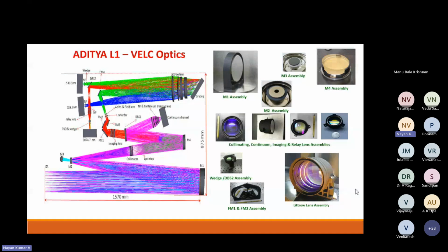And then we also had a silicon carbide mirror just to throw out that central disk, because this is an internally occulted system where the solar disk has to be thrown out, and we use only the corona for subsequent studies. So we made a silicon carbide mirror also with the help of ARCI. We got CVD coating done on that sintered silicon carbide, and then developed a polishing recipe to get this mirror to very low roughness.